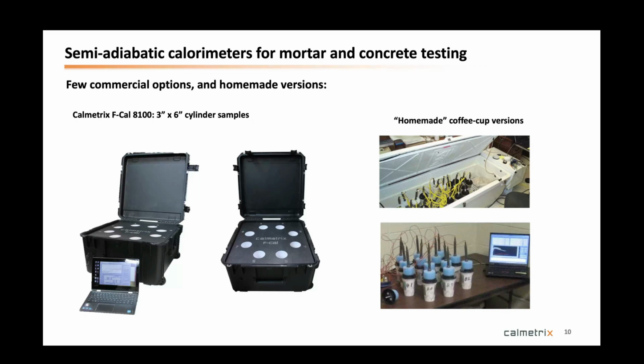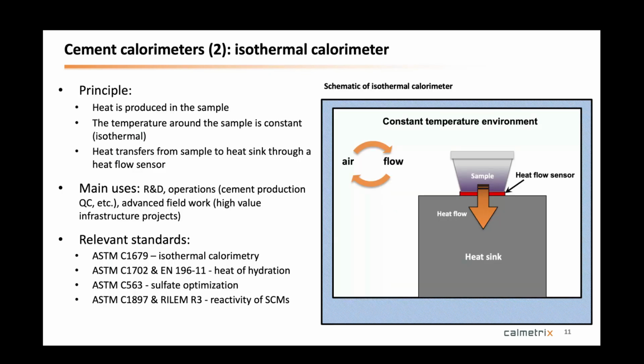And then you have isothermal calorimeters. They're a little bit more sophisticated. And those ones, you maintain the sample at a constant temperature. It's a very, very constant temperature, very much within plus or minus 1,000th of a degree. And here you can test a sample and look at the heat release in those very repeatable conditions. It's really mostly about repeatability. And you have a number of standards that are listed on the left, and you have more in other countries too. ASTM standards and EN standards for different applications that, again, a lot of you are familiar with.